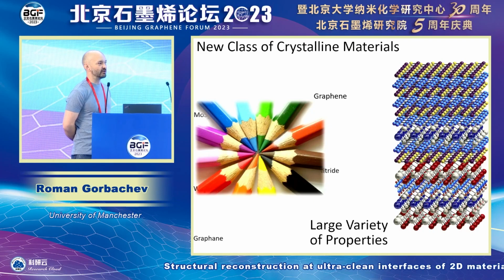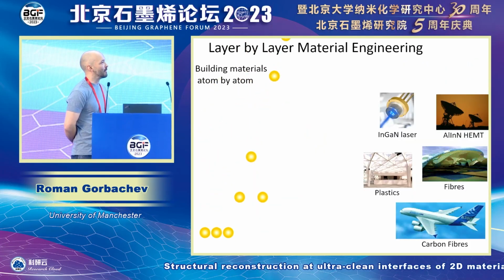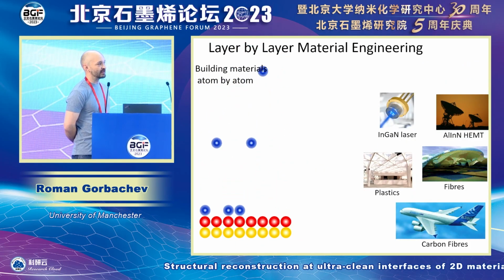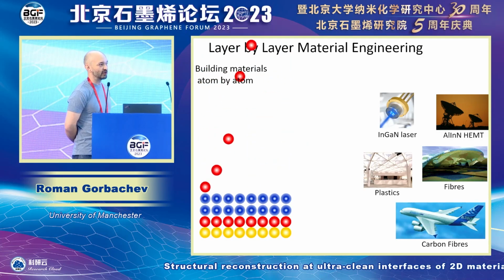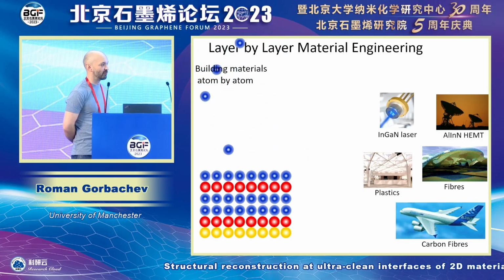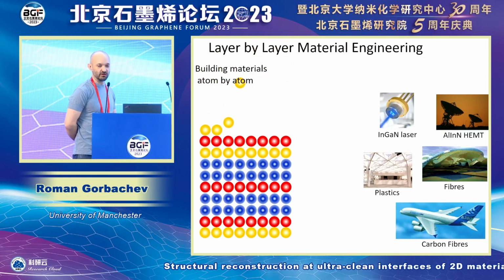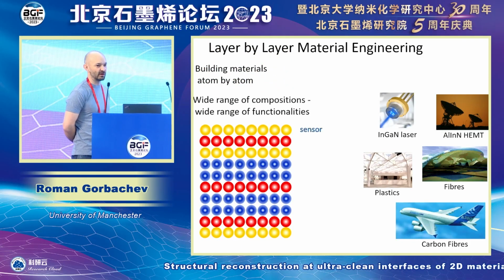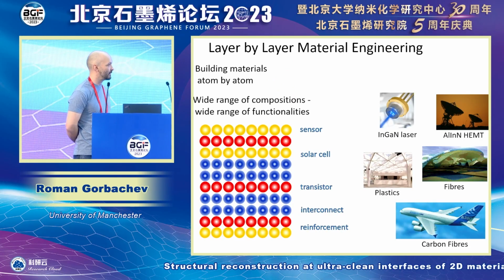And the key really is that you can take superconductors and topological insulators and look at the beautiful physics at the interface in between without really spending years learning to grow this kind of system. And the idea, again, is coming from molecular beam epitaxy, where you can grow these materials layer by layer. Only now you have much, much greater space to explore because you have so many more materials and you don't need to worry about lattice matching in the growth.